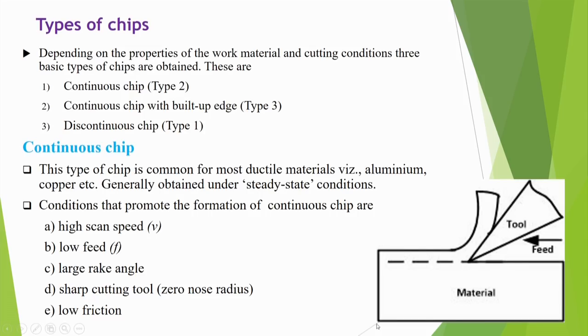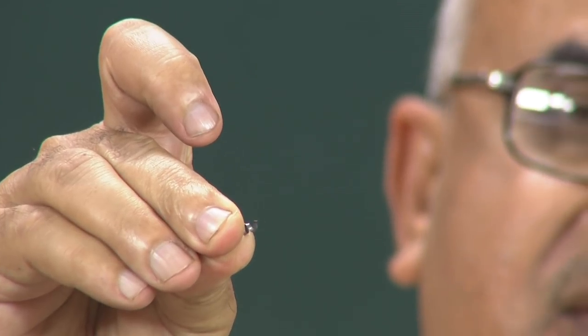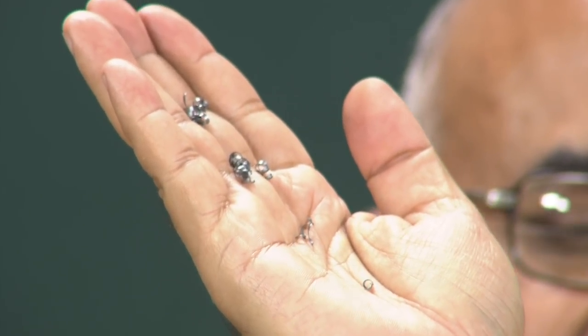Then we can get continuous chips with built up edge. That means there can be adhesion of the chip material on the tool due to high pressure and temperature. On the tool itself, you can observe that some built up type of edge will be there. These are not desirable because sometimes it gets stuck and then it gets broken. So this deteriorates the job quality and sometimes also increases the wear of the tool. So this is called type 3 chip. Then there are discontinuous chips. Discontinuous chips are of very small fragments. You see, very, very small. Perhaps it will be difficult for you to see from a distance. Small chips, they get broken. These are called type 1 chips.